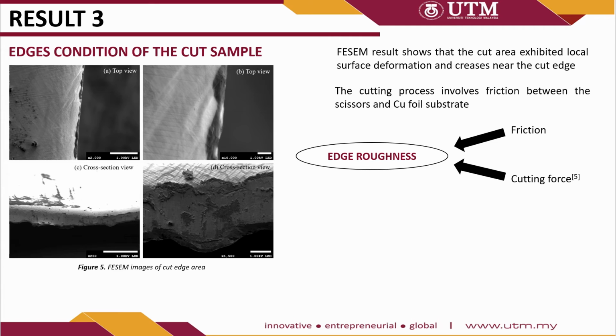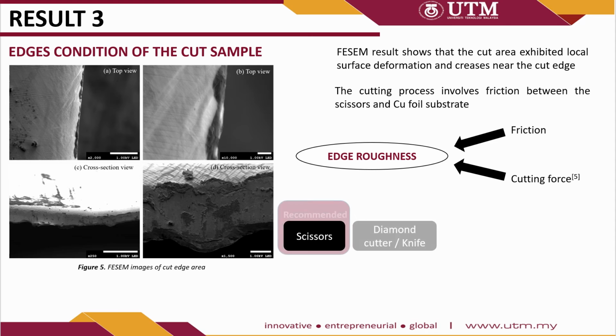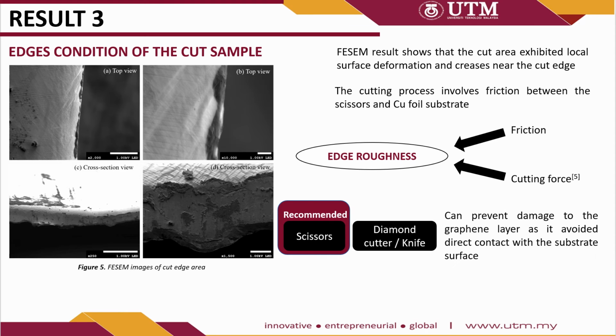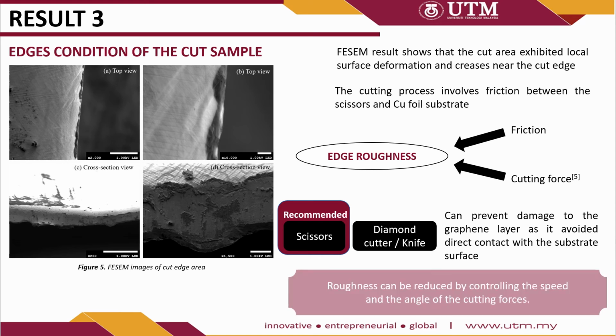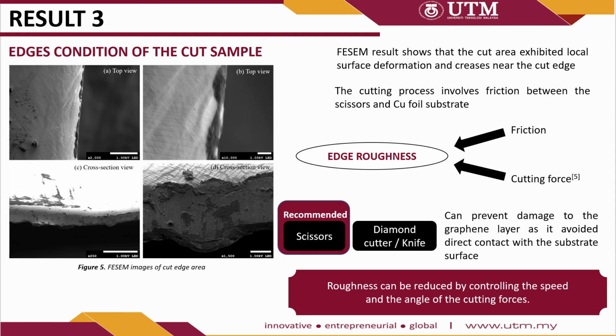Although cutting the substrate using a pair of scissors produces edge roughness, this method is still recommended compared with cutting the substrate using a diamond cutter or knife. This is because this method can prevent damage to the graphene layer as it avoided direct contact with the substrate surface. The roughness, however, can be reduced by controlling the speed and the angle of the cutting forces.